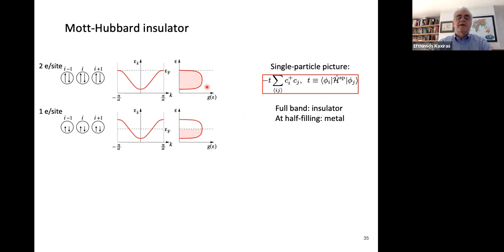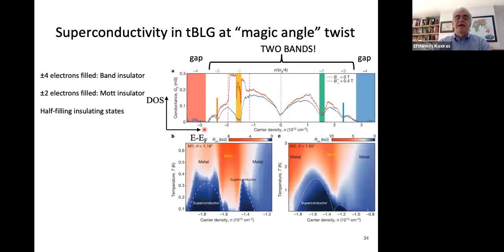So in a very schematic way, a single band fully occupied with two electrons per site would look like that. A band half occupied, with half an electron spin up and half an electron spin down per site, would look like that. But there's no way to develop a gap in the middle of such a band, as you see here. So here's one band with a gap in the middle. Here's another band with a gap in its middle.